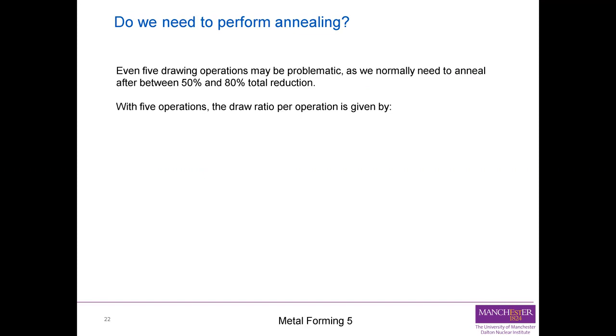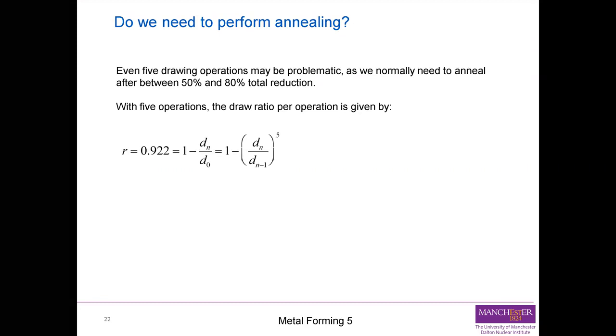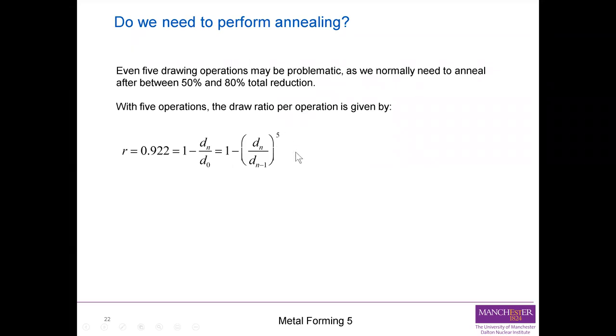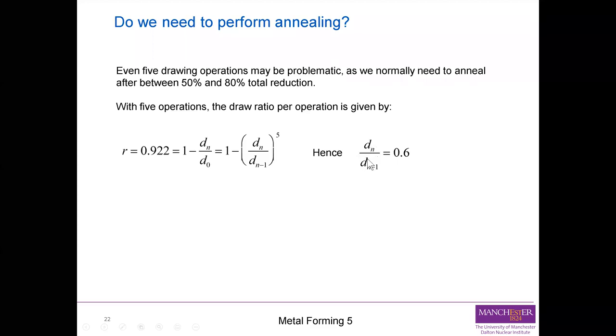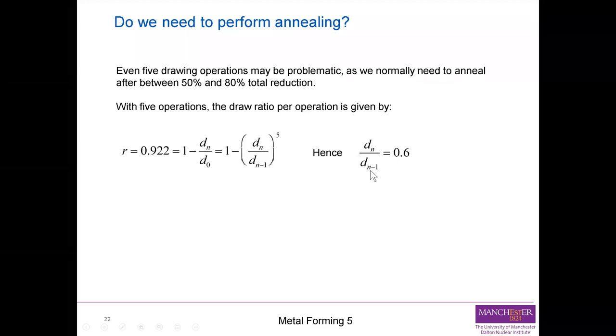So with five operations, the draw ratio for operation is given by the equation below, which is R equals 0.922 equals 1 minus Dn over D naught, which again, by the same substitution, is the same equation as I said before, but this time we are using n being equal to what we calculated before, which is the new value 5, whereas before it was an unknown value. And now this gives us that Dn over Dn minus 1 equals 0.6.